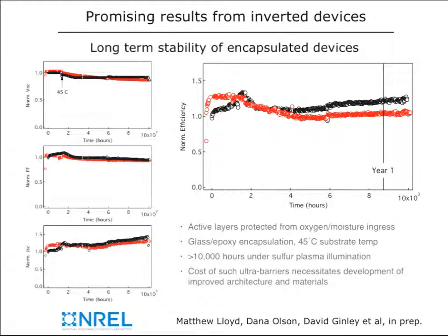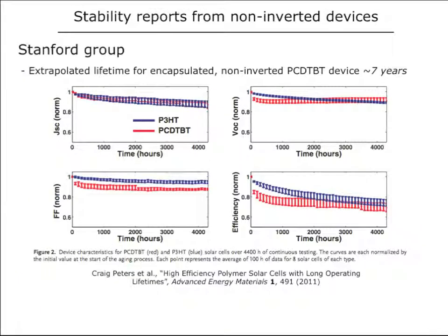We can also do that with encapsulated devices, where you take the same device and encapsulate it between glass, a very expensive encapsulation scheme. And the device is actually completely stable. In fact, it is increasing in behavior past 1 year. The extrapolated lifetime for this is now greater than 10,000 hours, and is still apparently going up at the 1 year point. So the point is that good encapsulation removes a lot of the oxidation processes, and the intrinsic polymer can be very stable.